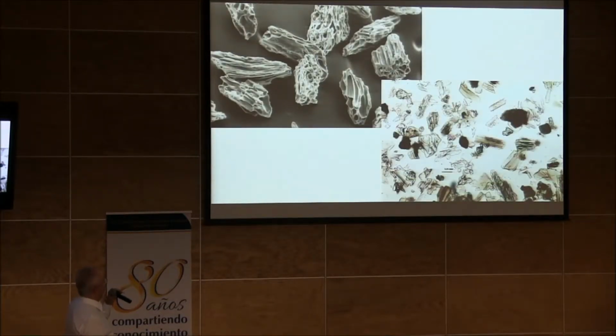Now this, finally, is a picture of what we're talking about the whole time. These are pyroclasts. These are fine-grained samples of exploded magmatic systems, volcanic ash. And what you can see is two different pictures of them. You can see on the upper left an electron microscopy picture, which allows you to see very nicely the morphology of these particles. So you can see a fair degree of complexity in the morphology of these particles. Essentially what you see, everything hard and solid that you see on the upper left is glass with embedded crystals, whereas what looks like holes, I hope looks like holes to you, is where the magmatic gas was residing at the point of explosion. Okay?